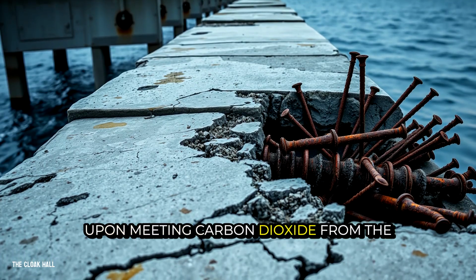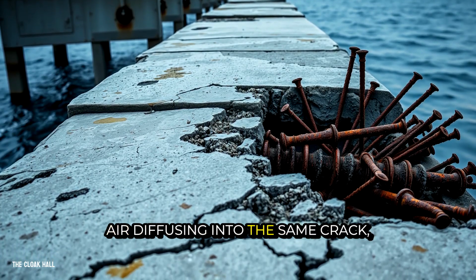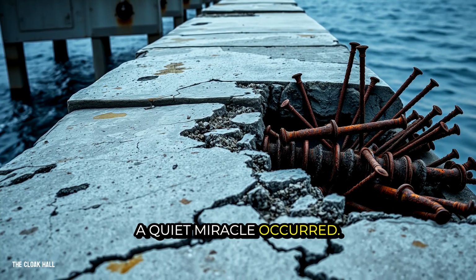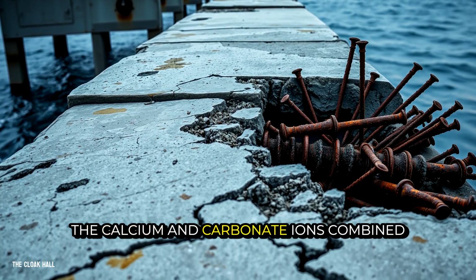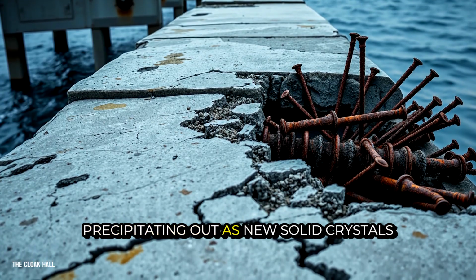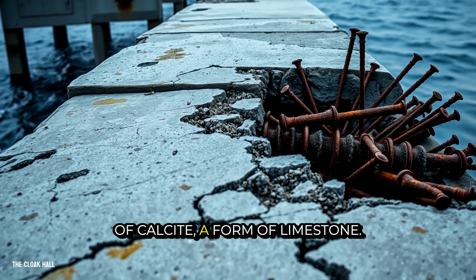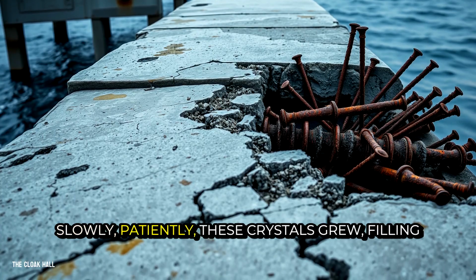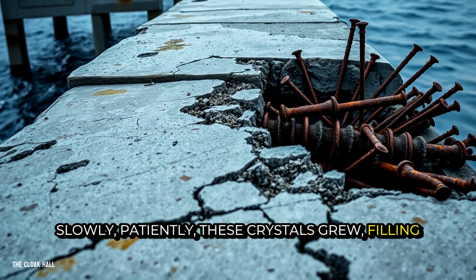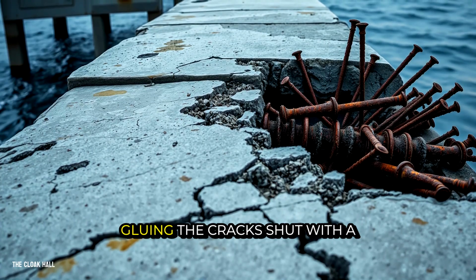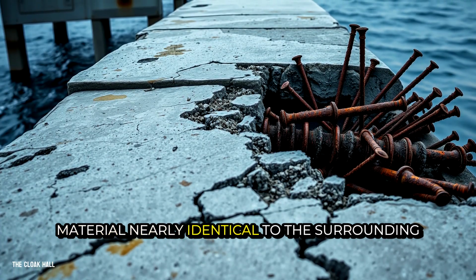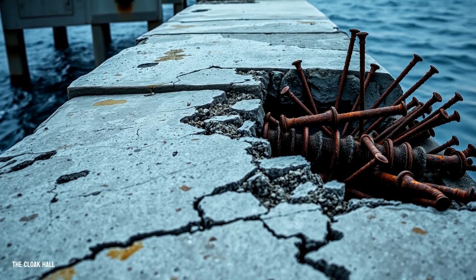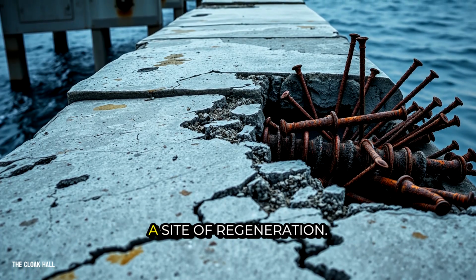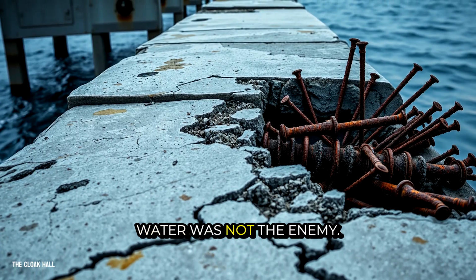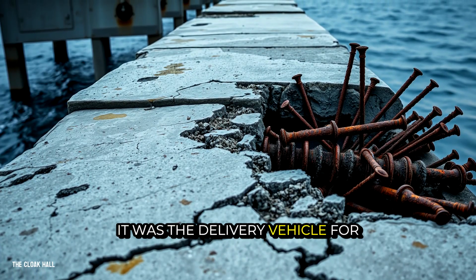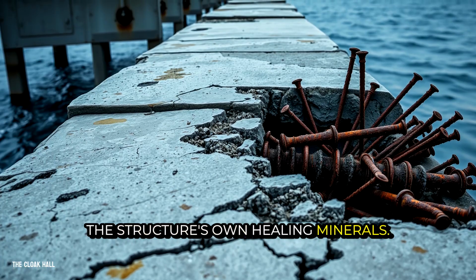Upon meeting carbon dioxide from the air diffusing into the same crack, a quiet miracle occurred. The calcium and carbonate ions combined, precipitating out as new, solid crystals of calcite, a form of limestone. Slowly, patiently, these crystals grew, filling the void from the walls inward, gluing the crack shut with a material nearly identical to the surrounding stone. The weakness had been transformed into a site of regeneration. Water was not the enemy, it was the delivery vehicle for the structure's own healing minerals.